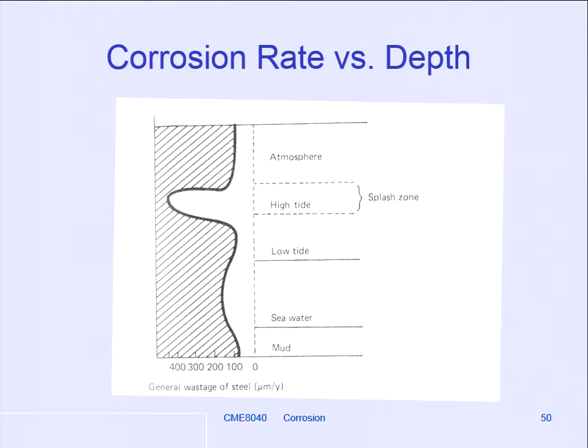There's a tendency to forget about, as we had in our earlier slides about classification of corrosion sites, mists and fogs and splashed water will still cause corrosion. So you're still going to get corrosion in the tidal zone. And it's that water droplet, if you like, on the bit of steel with the large oxygen differential across it will give you the pit. I mean, this is areas of a steel pile that would only be exposed for an hour or two every 2 weeks. Right in the bottom of the pile.